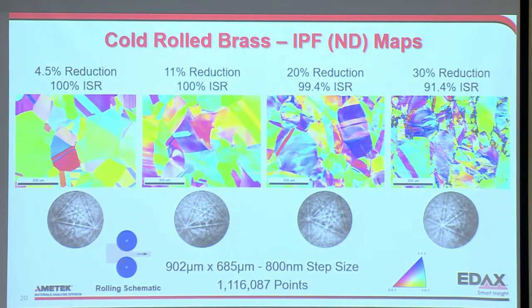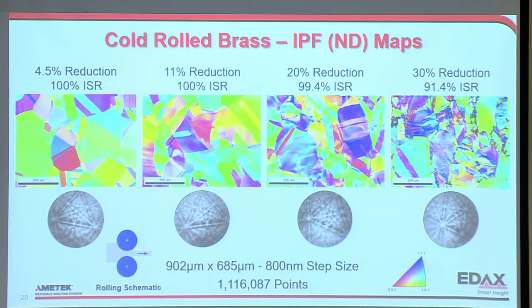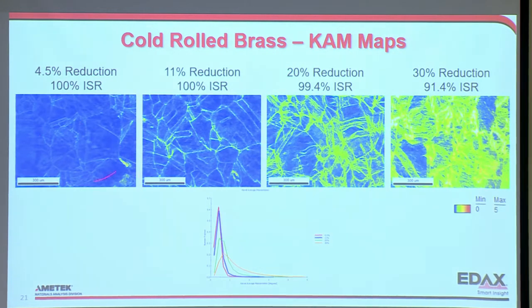Another deformed sample. This is 30% cold rolled brass, and we're still getting great results off the camera. And here's, I haven't talked about this, a kernel average misorientation map, which is a way of capturing deformation in the sample, and you can see we can capture that at these high speeds.